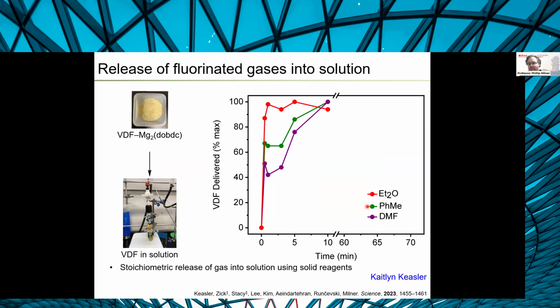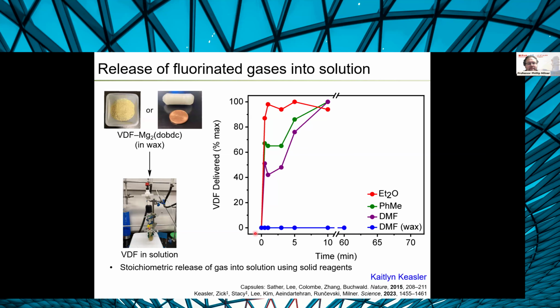But we wanted to see if we could do even better than this. Can we actually control exactly when the gas is released into solution, which would be even better for being able to set up reactions. So what Caitlin found she could do is take this gas-loaded MOF and actually pack it inside of a little sealed wax capsule, which protects it from air and moisture here. And now you can toss that capsule into solvent, and after an hour, we don't see any gas in solution because it's impermeable to the solvent. But she found that if she just sonicates it, the capsule breaks open, the MOF falls out, and then the gas is released into solution, and you can saturate it pretty much on demand by sonication.